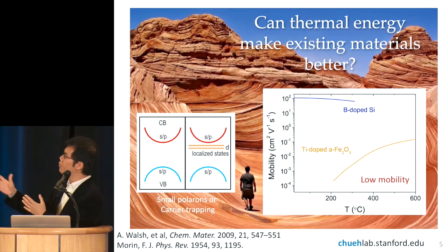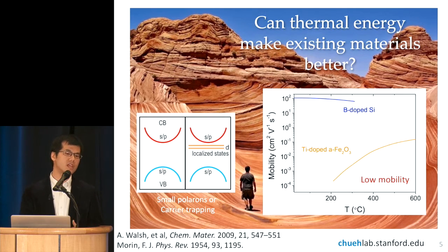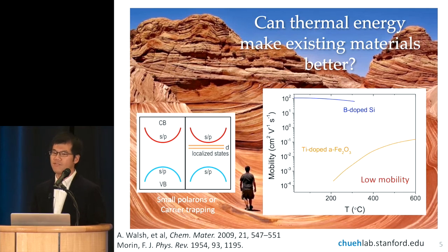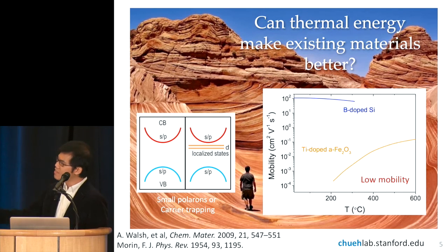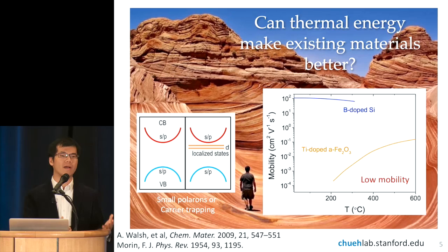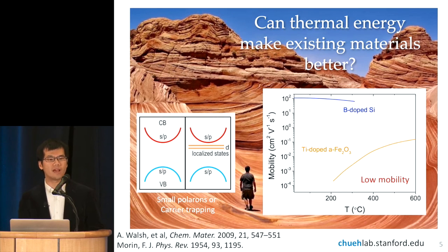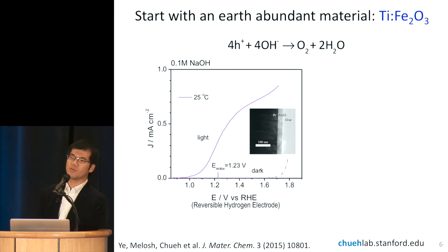So the idea was, well, can we turn some of these oxides into better performing oxides by cranking up the temperature a little bit? And the temperature here would, in principle, come from the inefficient absorption of sunlight, and then rather than throwing that away or by cooling the process, we simply turn that into activation energy to overcome some of the limiting process in the cells. So about 3 years ago, we started with iron oxide that is substituted with titanium, and we're trying to here perform the oxygen evolution reaction.